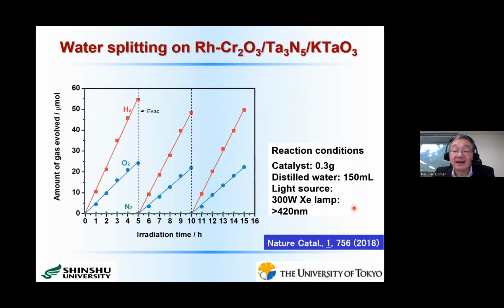Here I show the time course of the water splitting reaction. We use only distilled water and irradiated by only visible light. As you see here, both hydrogen and oxygen evolution takes place exactly in a 2:1 ratio. This is the first example which has succeeded in overall water splitting reaction based on tantalum(V) nitride materials.